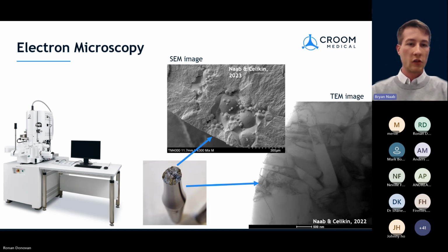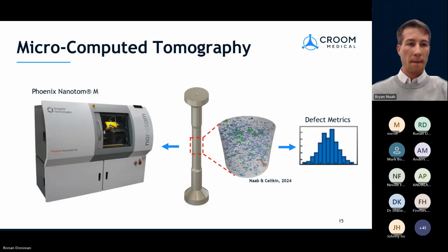SEM is more of a surface-driven technique, so it's quite useful for analyzing fracture surfaces and trying to identify certain defects which caused failure. Whereas transmission electron microscopy is essentially a nano imaging technique, which is very useful for looking deep inside the microstructure and trying to infer any property-process relationships there. Another technique which is quite relevant on this topic is micro CT scanning.